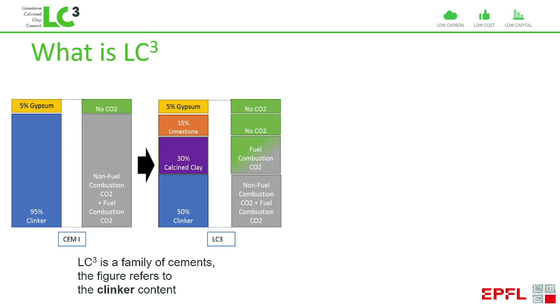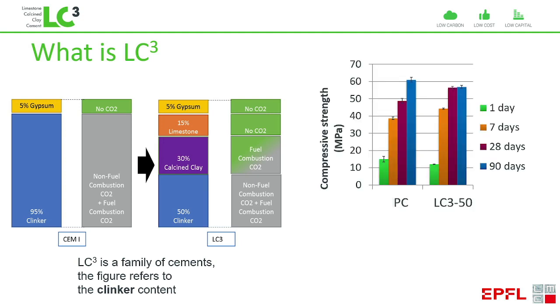So on the left there, we have conventional clinker, which is producing a lot of CO2. In LC3, we can replace at least 50% of that clinker by other materials. So we replace about 30% with calcined clay, which has a little bit of energy for calcination, but much, much lower than clinker. And then the other part by limestone and gypsum, which have no CO2.